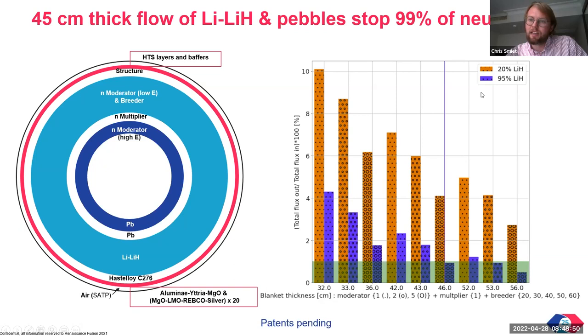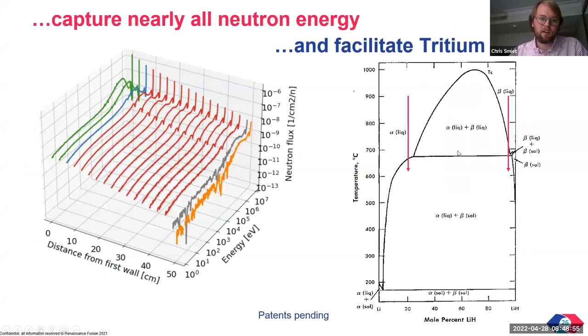We find that it's most effective using 95% lithium hydride. There's also a very interesting phase diagram that lithium hydride has, because it comes in different phases at different temperatures. So at above 700 degrees Celsius, all of it is in the alpha phase, but there's also portions of the diagram where it has both a liquid and a solid phase, alpha and beta, in which one, the beta phase, is much higher in lithium hydride. So this gives us a way to separate the lithium hydride.